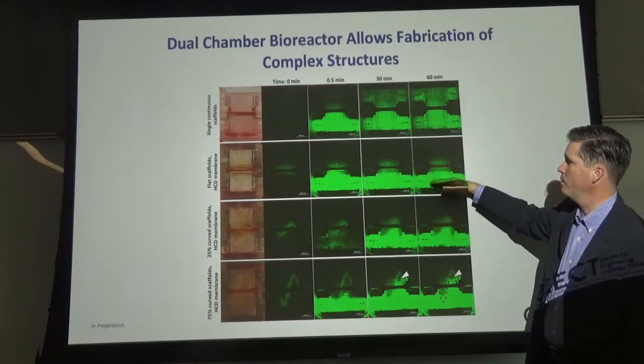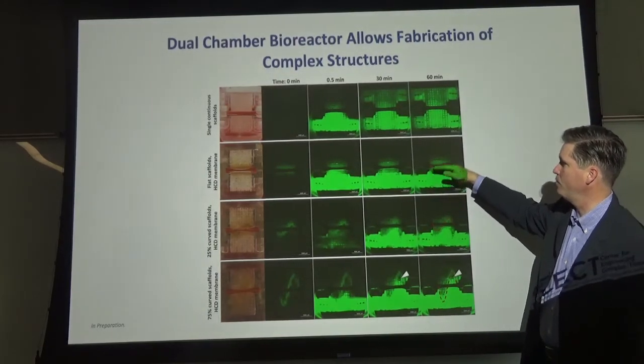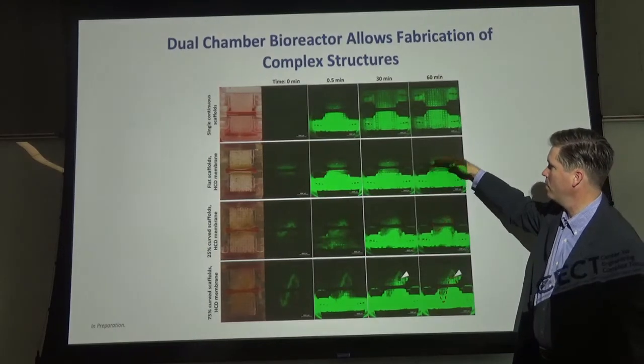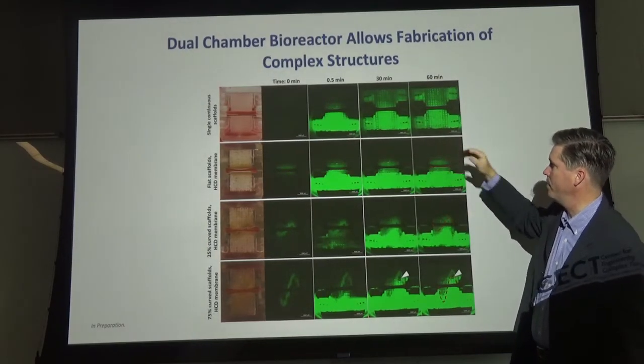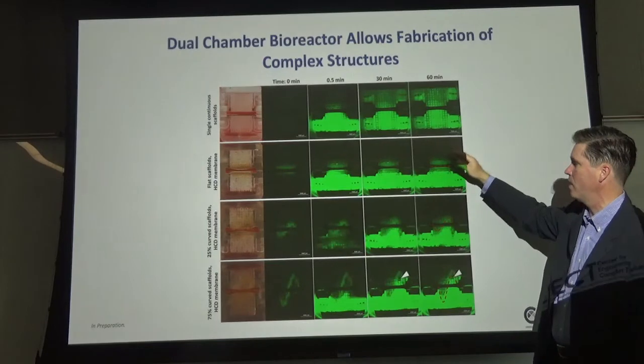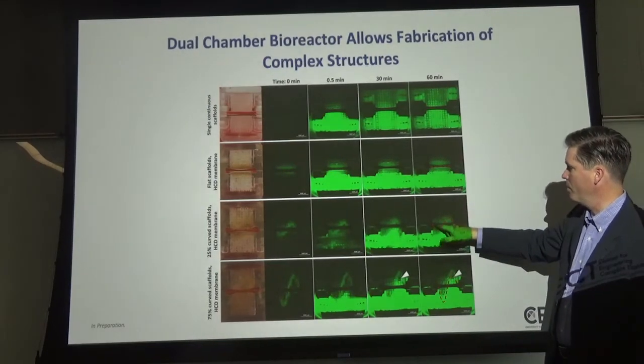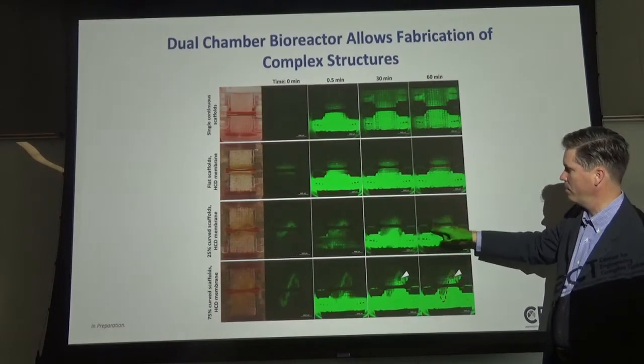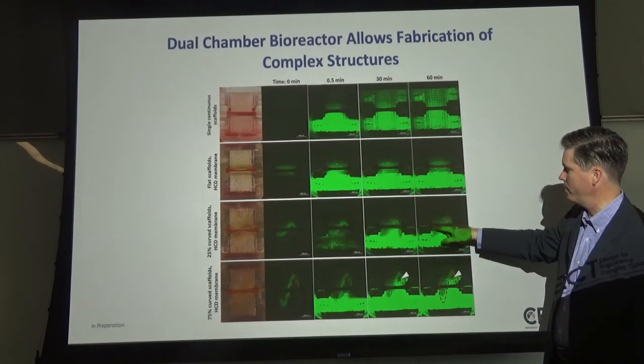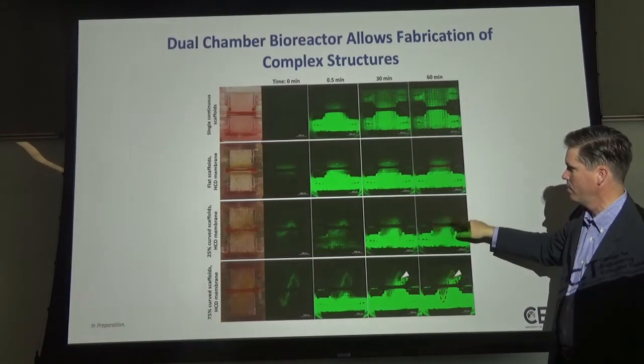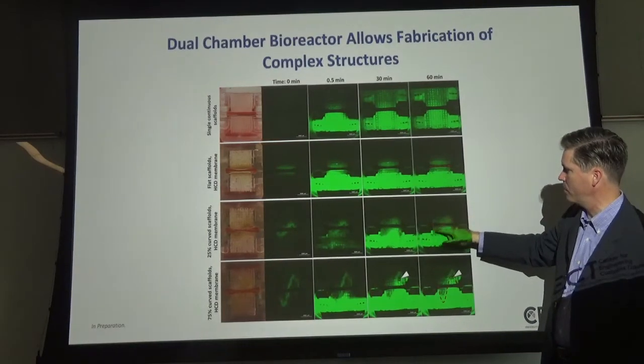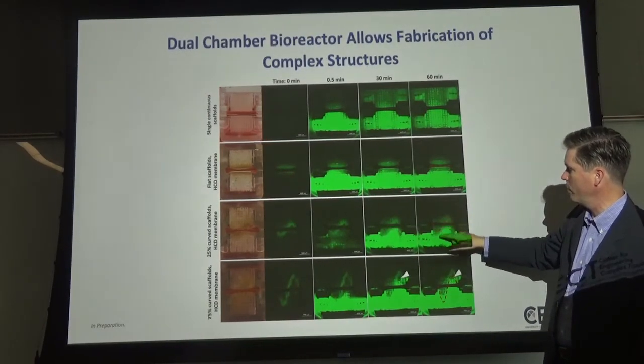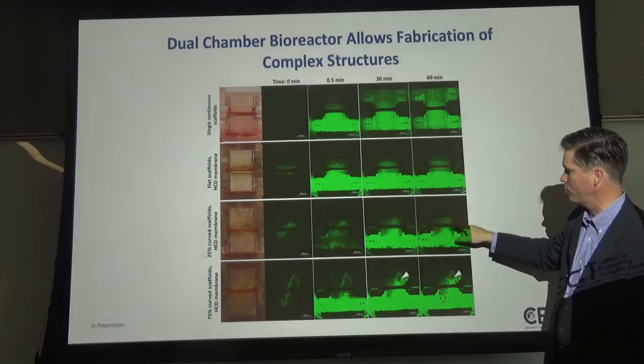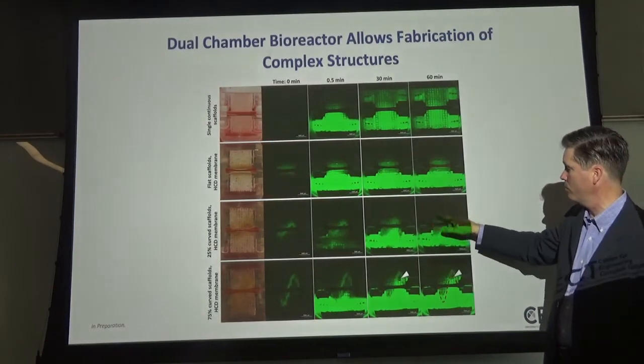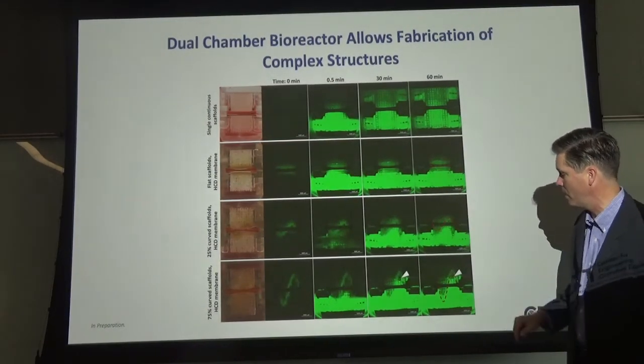Here's two different scaffolds, but with a membrane, a very tight membrane that's preventing diffusion from the bottom chamber up to the top. And here's a membrane where we have a 25% curved scaffold that's separating the two chambers. You can start to see some structure in the bottom. The bottom chamber is equally, you can see that in the top chamber.